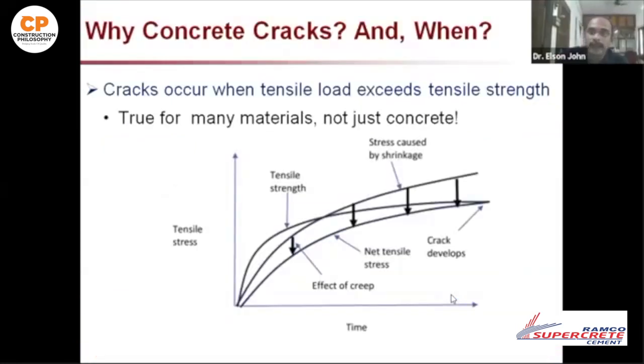So again, why does concrete crack? As Sunita was mentioning, concrete cracks when the tensile load exceeds the tensile strength of the concrete. That is true for all materials, not just concrete. But the specialty with concrete is that it starts cracking before the strength is attained. In the plastic stage itself, there is a possibility of cracks.